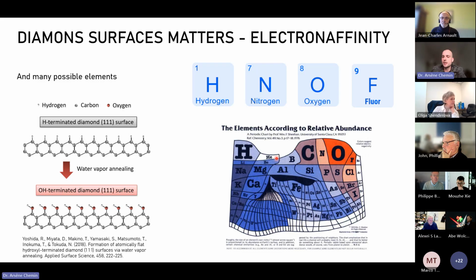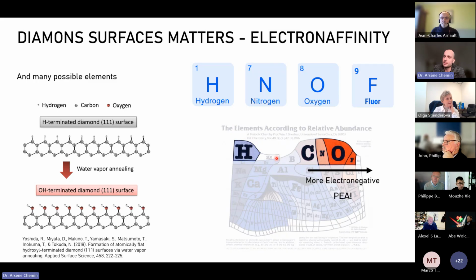Now, if we come back to this table here, you can see that the different colors of the elements correspond to the electronegativity of the atoms. And depending on the element that you will bond to the surface of the diamond, you will actually change the surface properties. If you look to the right side of the carbon, you have nitrogen, oxygen, and fluorine, which are more electronegative than the carbon, which means that they will tend to pull electrons out of the carbon atoms, and that will lead to a positive electron affinity of the surface.